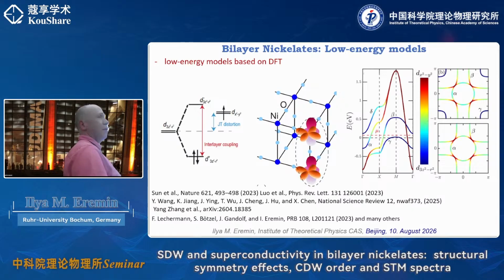is still crossing the Fermi level, or maybe not. That's something that people are still discussing. While the delta pocket, if you look at the on-site energies, originates initially from the dz², but it changes color, so it means there is a lot of hybridization, but it doesn't cross the Fermi level directly. It's only degenerate exactly along the M-gamma point. And then you have the dx²-y².